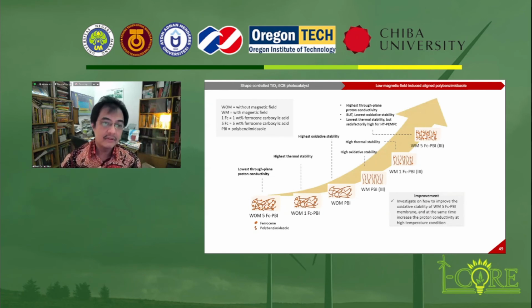Without magnetic treatment, the membrane with the high number of ferrocene shows the lowest through-plane conductivity. Nevertheless, once the magnetic field was introduced, the membrane shows the highest conductivity. Thus, this creates a continuous pathway for the proton conduction and increases the proton conductivity through the membrane. So this is the conclusion: we can align the polymer, polybenzimidazole in this case, with the magnetic field, so that we can increase the proton conductivity to give better performance of the fuel cell.